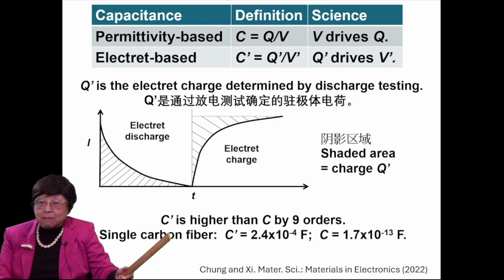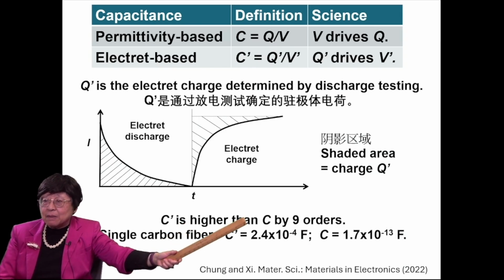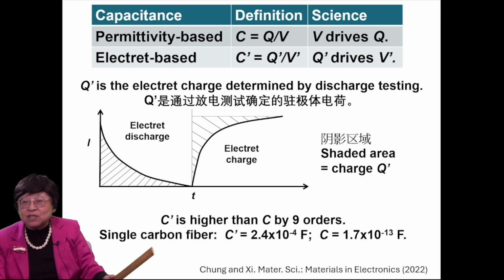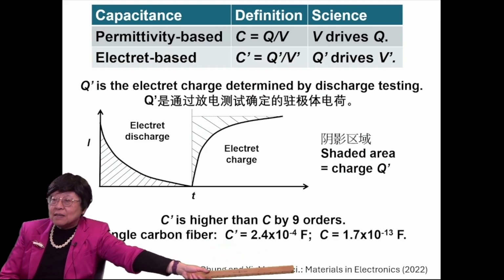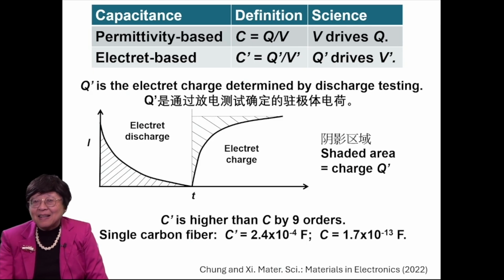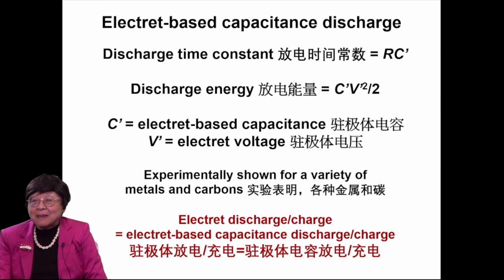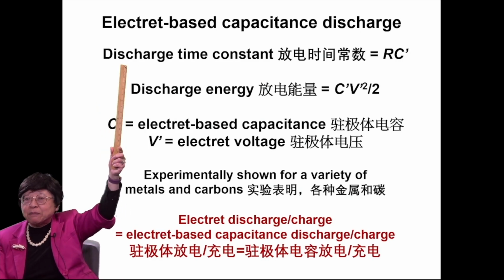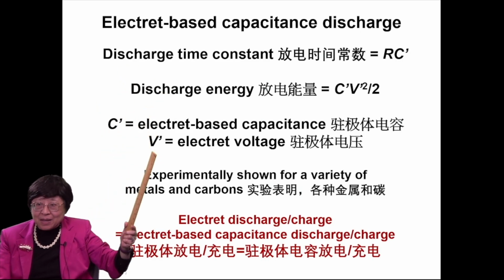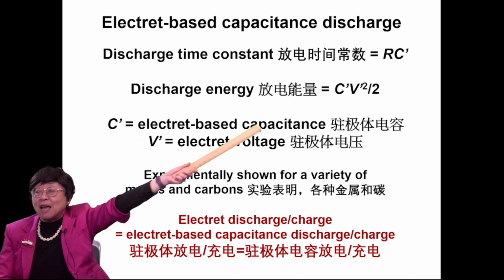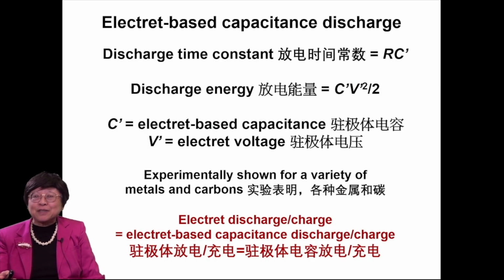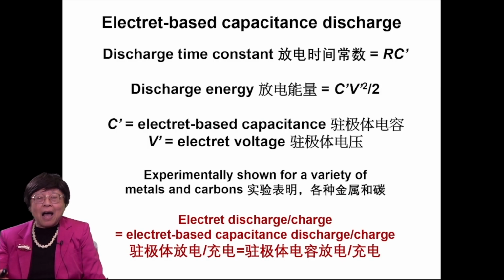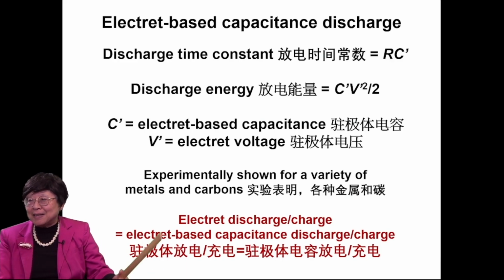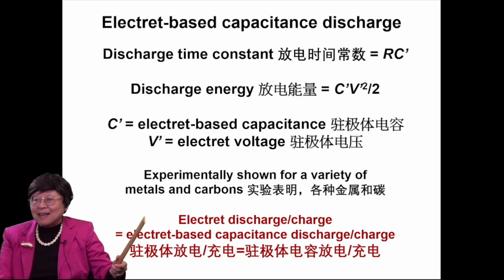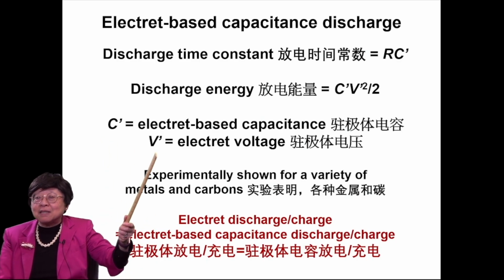The C prime, the electret-based capacitance, is higher than C, the permittivity-based capacitance, by 9 orders. For single carbon fiber, C prime is 2.4 times 10 to the minus 4 farad, and C is 1.7 times 10 to the minus 13 farad. Okay? So huge electret-based capacitance. The electret-based capacitance discharge involves a discharge time constant, which is equal to RC prime, and discharge energy equal to half C prime V prime square. Conventional capacitors would be RC and CV, half CV square, right? But now instead of C is C prime, instead of V is V prime. C prime is the electret-based capacitance, V prime is the electret voltage.